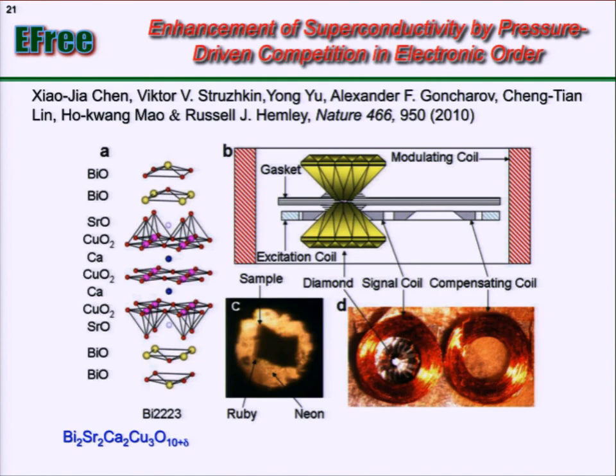Okay, and now we talk about what is known for the oxide superconductor. This is still the highest Tc superconductor, but the way you can improve the oxide superconductor is by changing the oxygen deficiency. That's called doping. By changing the oxygen deficiency, you can have underdoped, overdoped, and in between you have optimal doping. So that's the one that usually has the highest Tc.